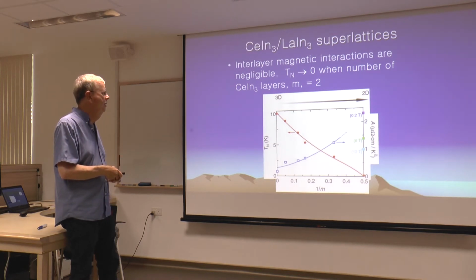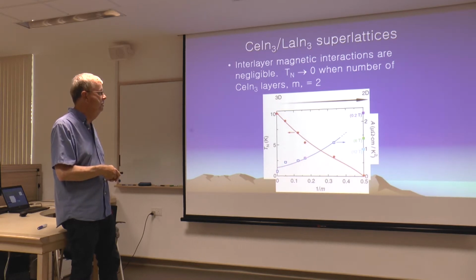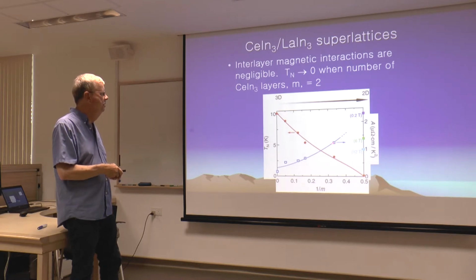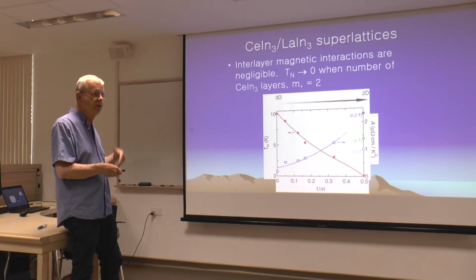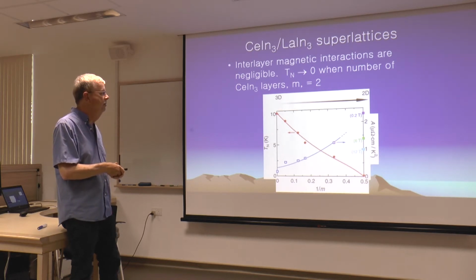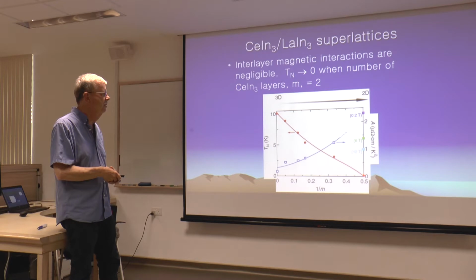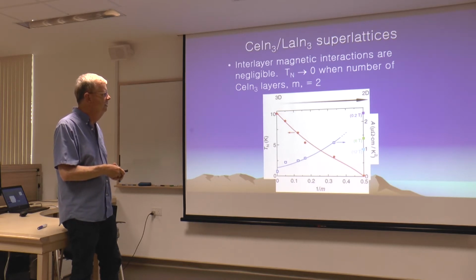And what was that? Well, that was the coefficient A in rho equal rho naught plus A T squared. So this says that the blue points are in a region where I have Fermi liquid behavior because I have T squared. And if I follow this down to 2 layers where there's no anti-ferromagnetism, and I put a little teeny field on, you can see that this looks like it extrapolates. But if I put a bigger field on, you can see this doesn't look like this has something to do with this extrapolation. So let's talk about the field dependence of this coefficient.